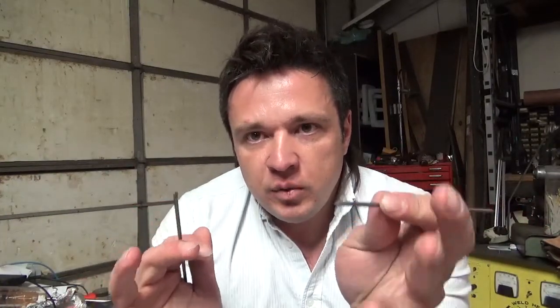Unfortunately, standard arc plasma has two big disadvantages. The first disadvantage is that lighting plasma arcs over about 1 or maybe 2 kilowatts and using electrodes bigger than about a quarter inch just doesn't work. The process breaks down, the plasma doesn't want to stay lit, and if you just crank up the power, it's going to kill your process. It doesn't work.